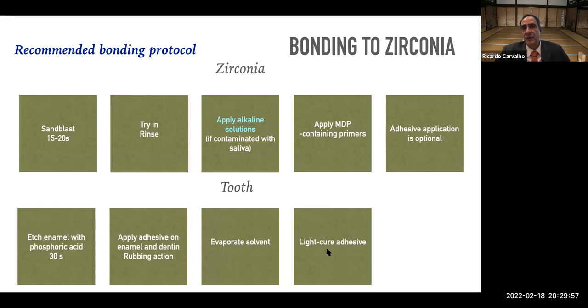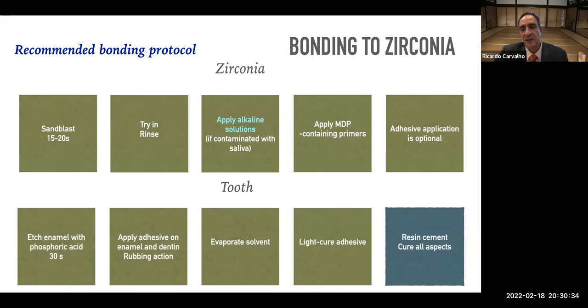And some people are concerned, well, if I light cure my adhesive, my crown will not fit. Well, if that is the case, probably you applied too much adhesive. Right? Because the adhesive layer is also supposed to be a thin layer, usually in the range of 30 to 50 microns. And that is not necessarily something that will compromise your fit, because when you are treating the ceramic surface inside, you are also removing material and allowing space for the adhesive to fit in there.